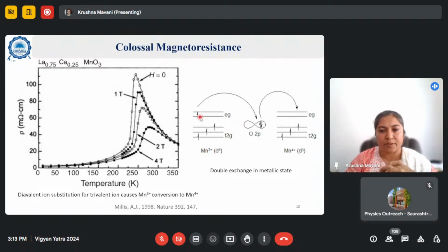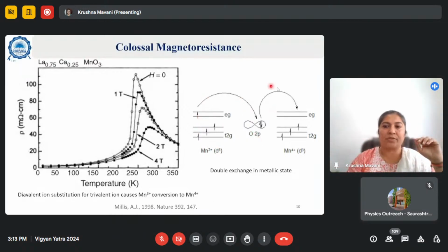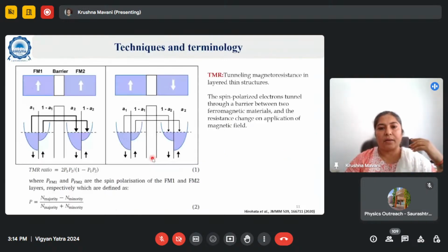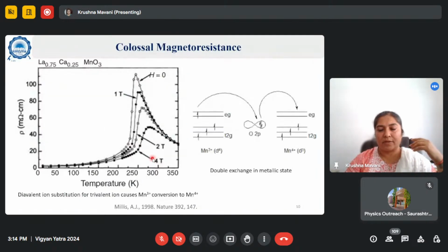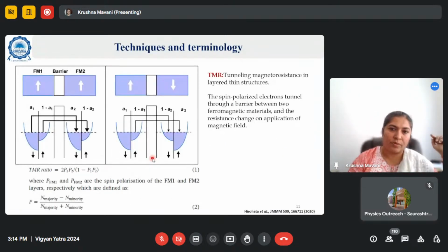Spins are aligned in parallel. So this scenario is possible when you have ferromagnetic spin, ferromagnetic exchange. So when more and more spins align, more and more double exchange of charge carriers is possible. So conduction increases and your resistance decreases. So as you apply more and more magnetic field, from H equal to 0, 1 Tesla, 2 Tesla up to 4 Tesla, this largely decreasing resistance is called colossal magnetoresistance, and since it is decreasing, it is called negative magnetoresistance.